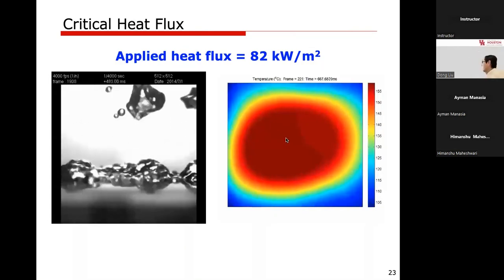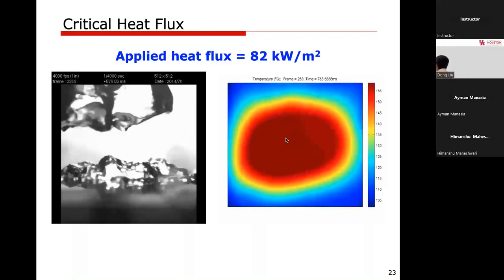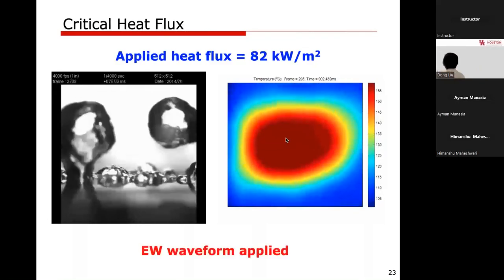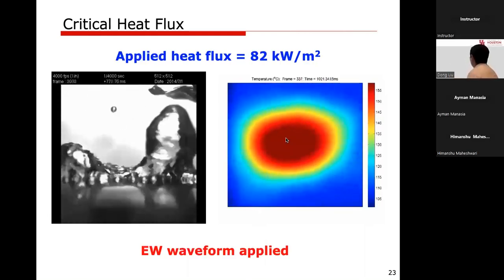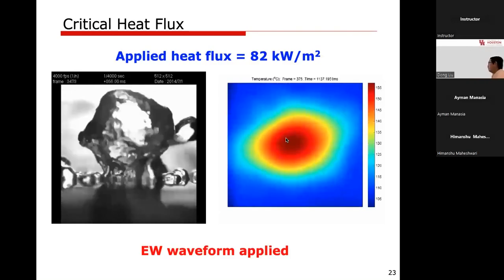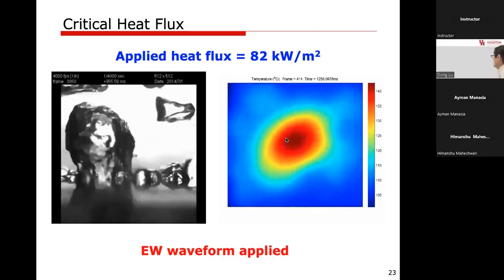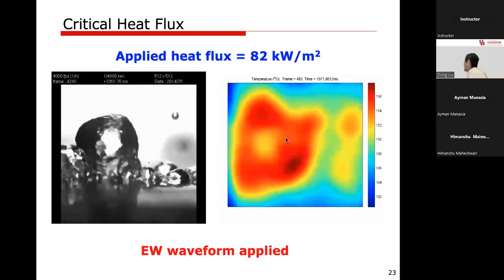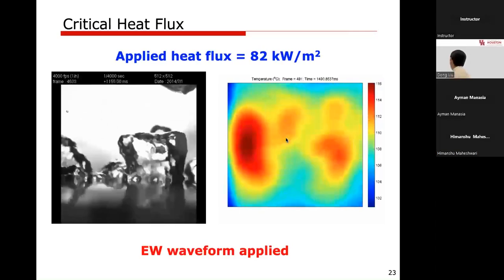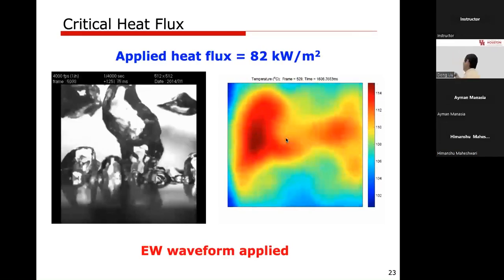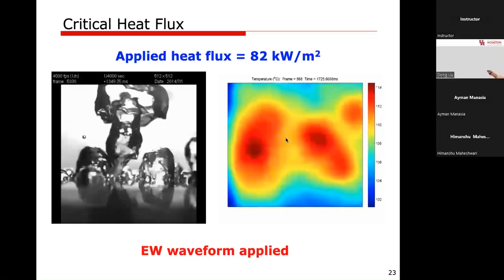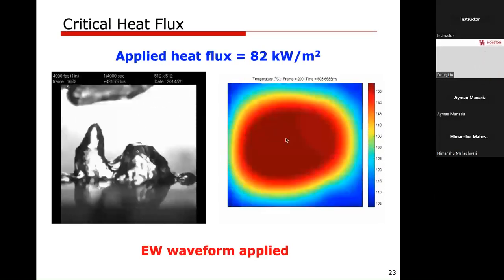Okay. Now, what's more significant occurs at the critical heat flux. So now this time, the heat flux is increased to 82 kilowatts per meter square. So let's see what's going on. Right. So you see now very clearly the surface is covered by a liquid film. Right? Now the big hotspot has a highest temperature of about 155 Celsius. So at some point we will trigger the electrical signal. Right? Okay, now you see this time the film breaks down into individual bubbles, and the big hotspot breaks down into much smaller pieces, and the maximum temperature reduces from 155 to 114, 112.